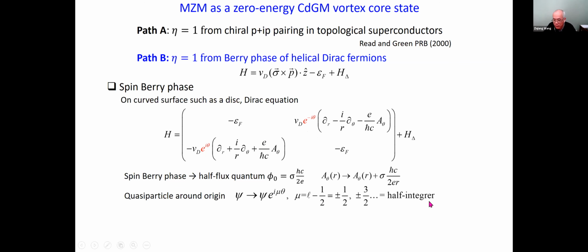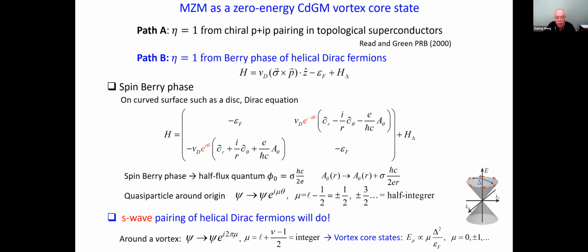a half-integer quantization. Now, if I make the Dirac fermion superconductor, and then look at the vortex core, this -1 here that came from the Berry phase is exactly the eta I needed to make this angular momentum quantum number integer. And in this case, I would have vortex core states, a sequence of vortex core states that are integer quantized and include the zero mode. And that's the Majorana zero mode. So in this sense, the s-wave pairing of helical Dirac fermions will do.